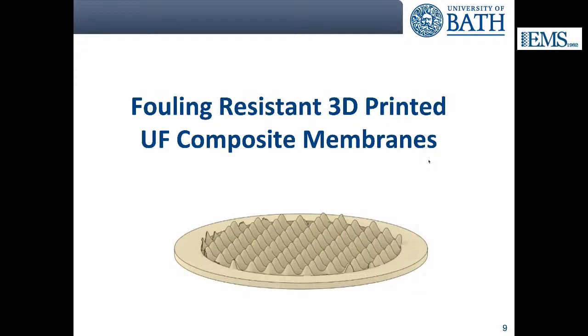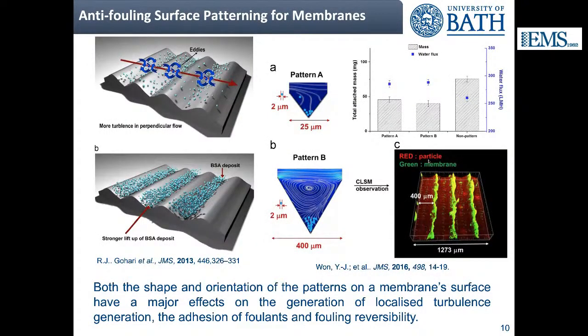The first part of the talk is on 3D printed ultrafiltration composite membranes. The idea behind this is membrane patterning, which has been around for a long time. What you see here are papers from about 10 years ago, where they used stamps to pattern an existing polymeric membrane to have this undulated structure, or, for example, a pyramidal pattern, where you could create these pyramidal stamps in the membrane. And what is interesting is that these undulations generate localized turbulence on the surface of the membrane, and that helps with reducing the adhesion of foulants and also in making it easier to dislodge the foulants when you're cleaning.